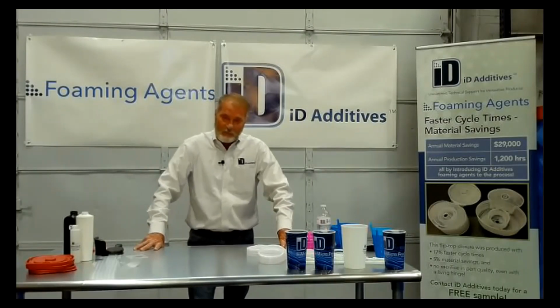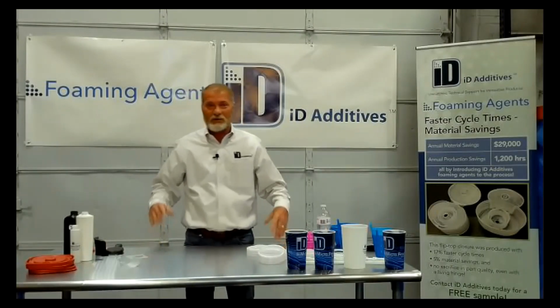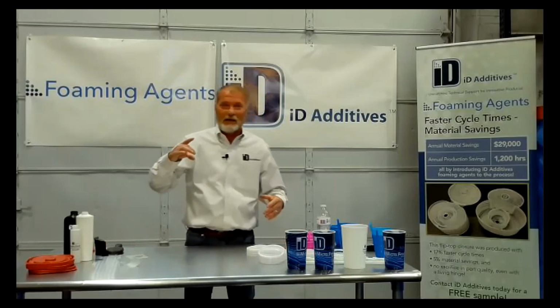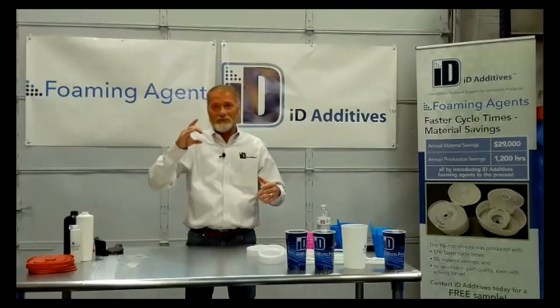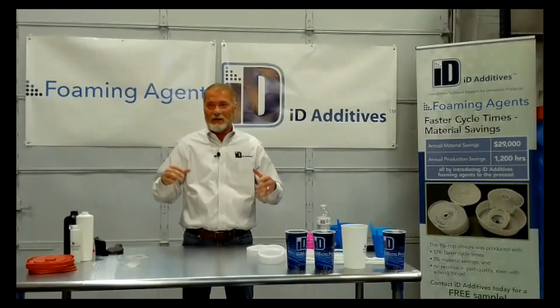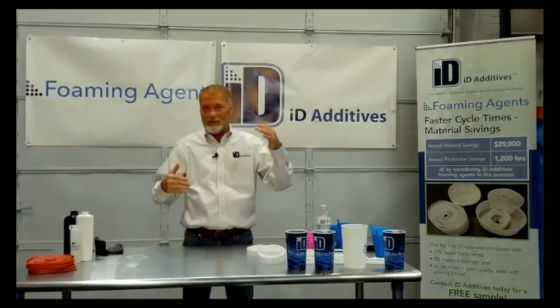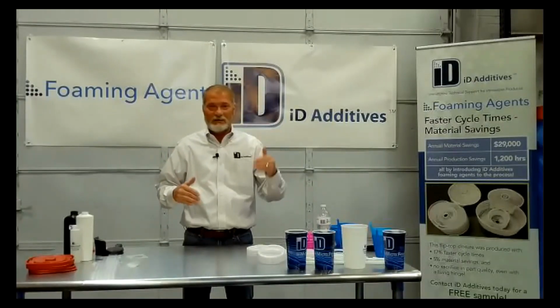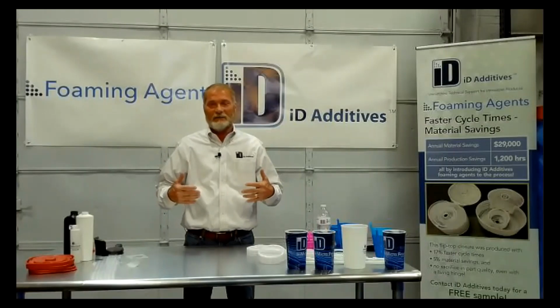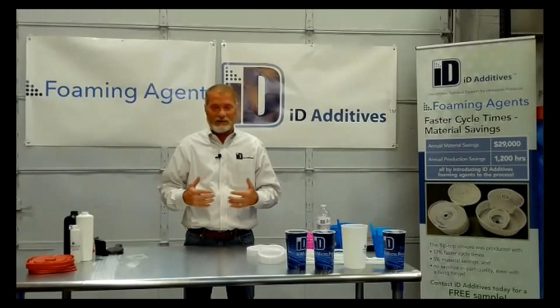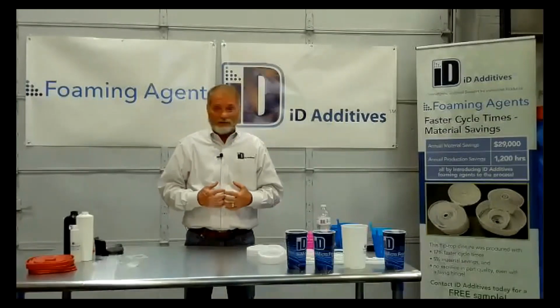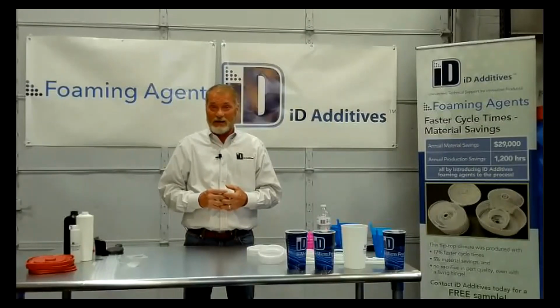Now, if you're going to run 0.3, you want to make sure you drop that nitrogen down until you start to go short, and then just bump it back up a little bit. That way you get a balance between 0.3 and whatever the nitrogen is. But I always recommend 0.5. And the reason you think 0.2% in that kind of business is a lot of money, by the way. But 0.2% in a 120-plus cc per gram gas, that's a lot of gas.